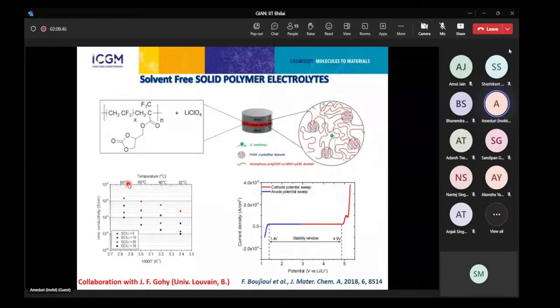You have a conductivity which is higher than 10⁻³ Siemens per centimeter, which is a challenge to reach. Now, the best are about 2 or 3 10⁻³. So we are in a good position in this way. And what is also very interesting is the good electrochemical stability at high potential. Usually now the tendency is to be stable at 5 volts. But you see at 5 volts, we have just a slight oxidation. If you go higher, of course, the oxidation is much higher.